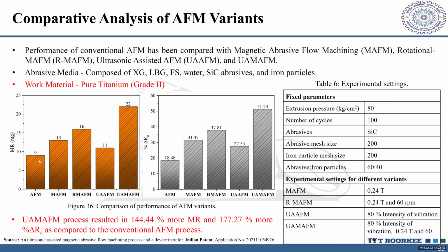For a conventional AFM, if there is 9 mg of material removal, we can have up to 22 mg of material removal within the same time. So it means we can improve the material removal by 144%. At the same time, for the percentage improvement in Ra, from 18% we can achieve 51% improvement, which means around 177.27% more improvement as compared to a conventional AFM. So these are the different variants: magnetic assisted flow finishing, rotary magnetic, ultrasonic assisted, and this is where our particular machine and our particular patent lies, which can give you very high dividends in terms of material removal as well as surface finish.